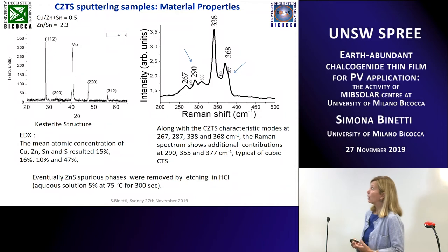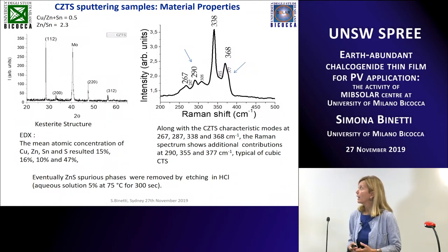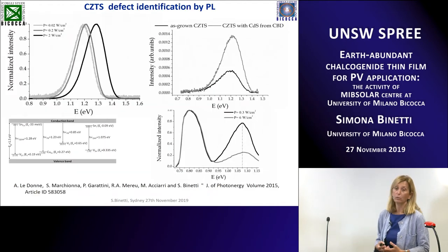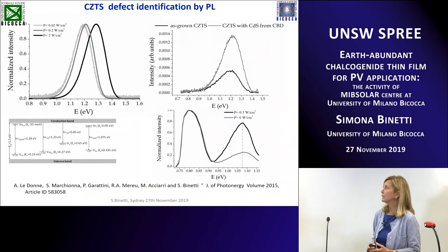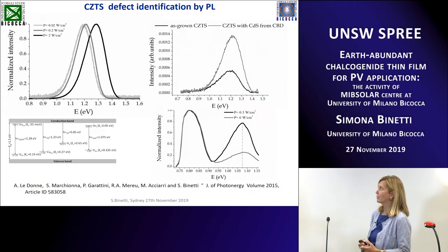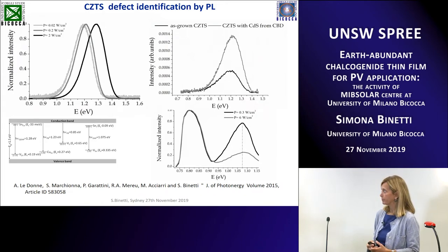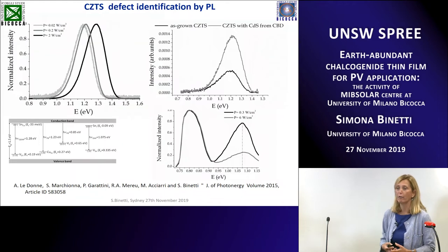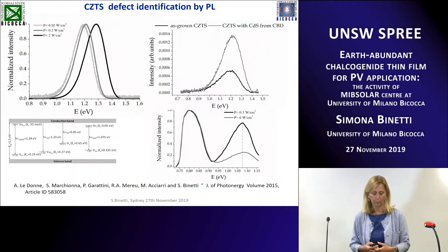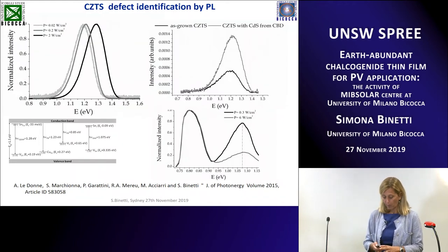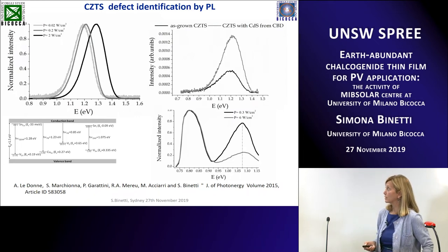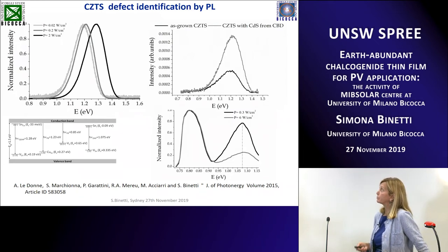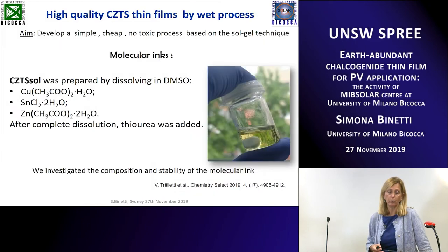We also performed a lot of photoluminescence on this material, and we have seen that there are a lot of defects, as you know, in this material, and we also have in our material a quite high defect band around 0.8 eV, that is most probably related to secondary phases in our material. So we decided to move forward to changing the deposition process, and our idea was to develop a completely